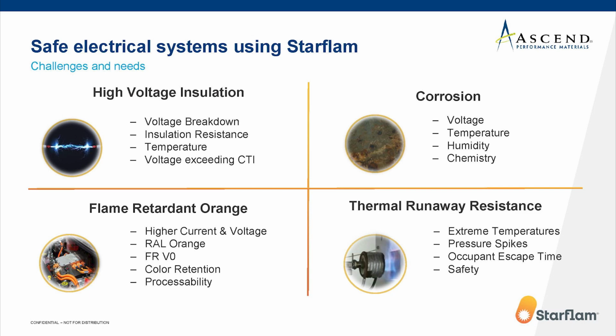So when we started out with developing these products, we were faced with a variety of challenges and needs. And the first is high voltage insulation, in our case, the polyamide. It's required to minimize voltage breakdown and provide insulation resistance. And it also has to perform at elevated temperatures over long periods of time. And it has to perform at high voltages, even exceeding the measured CTI of 600 volts. And CTI is comparative tracking index. We do know that groups are working on developing more realistic ways to measure tracking index at the higher voltages, but right now there's no established method in the industry.